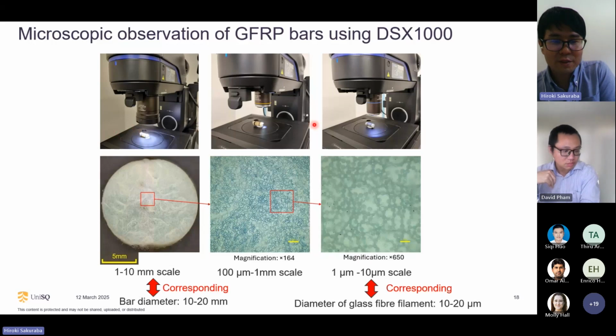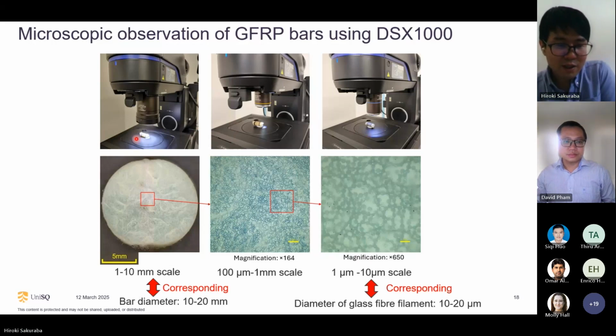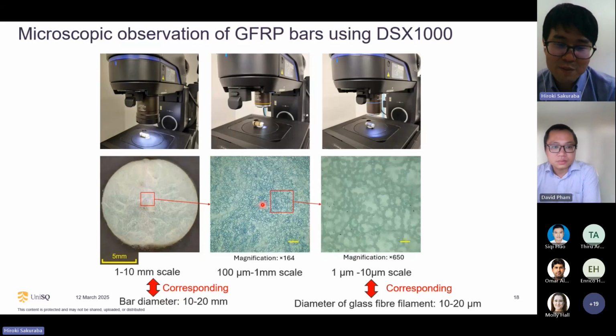many kinds of lenses which have different magnifications. For the first lens, we have a 1 to 10 millimeter scale microscopic lens. This really corresponds to the bar diameter of 10 to 20 millimeters, which is what we normally use. And then we can use another high magnification lens. This has a 100 micrometer to 1 millimeter scale.